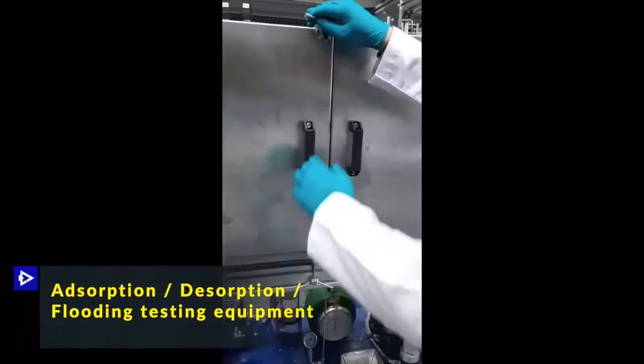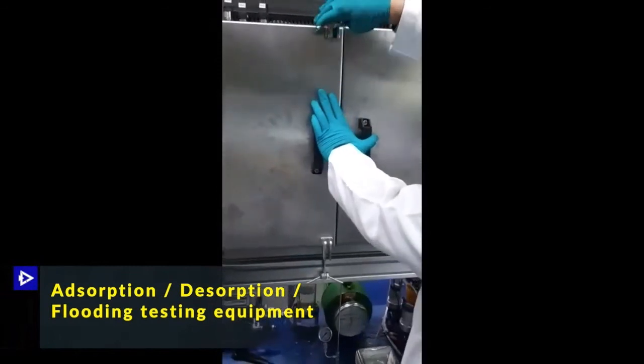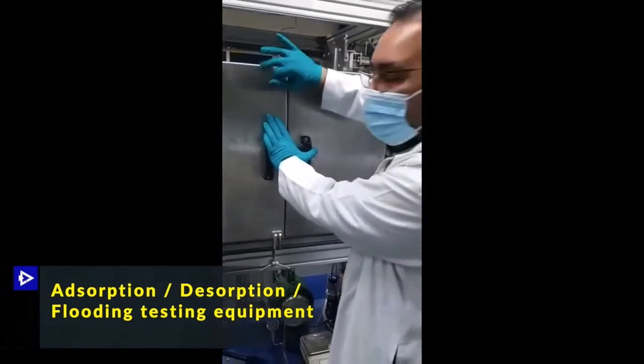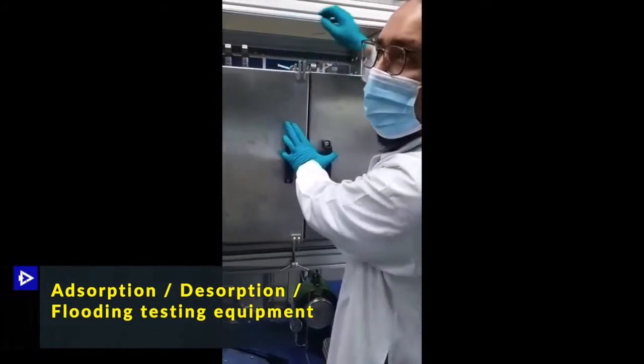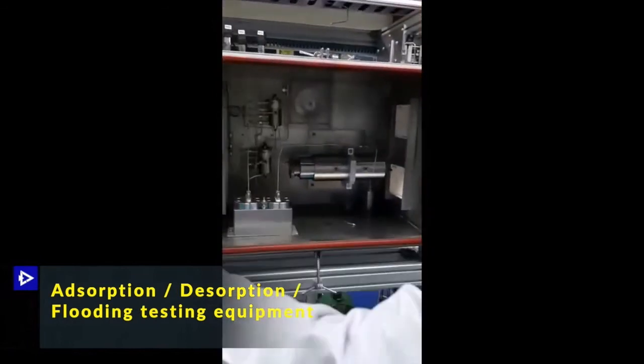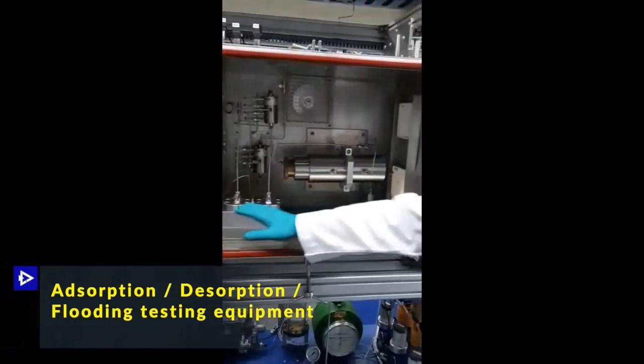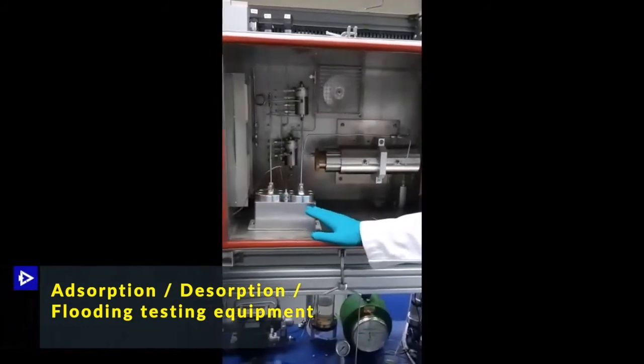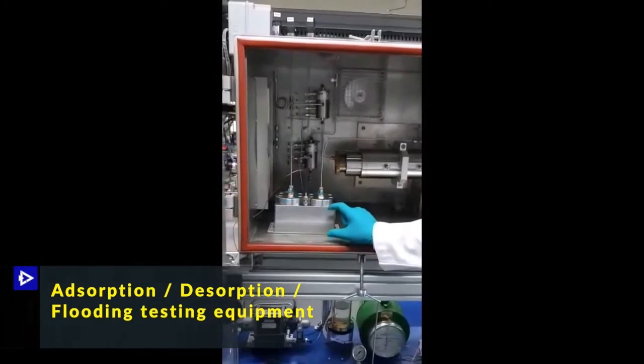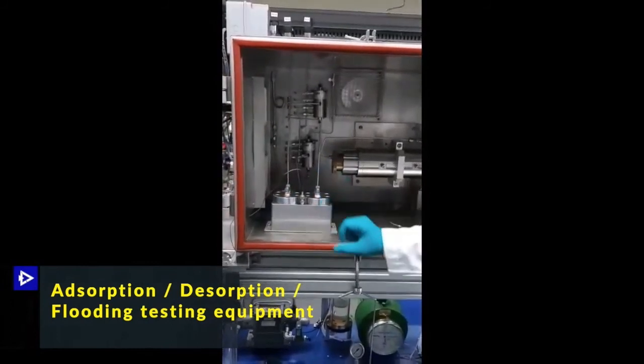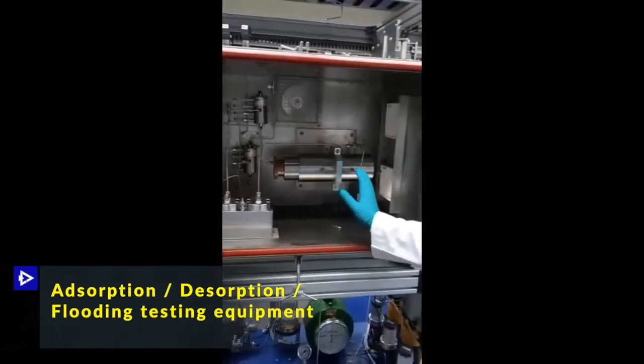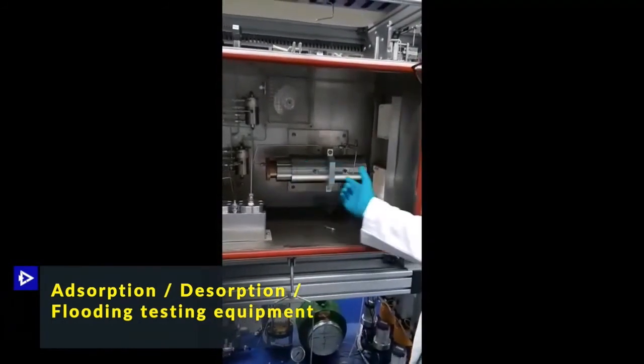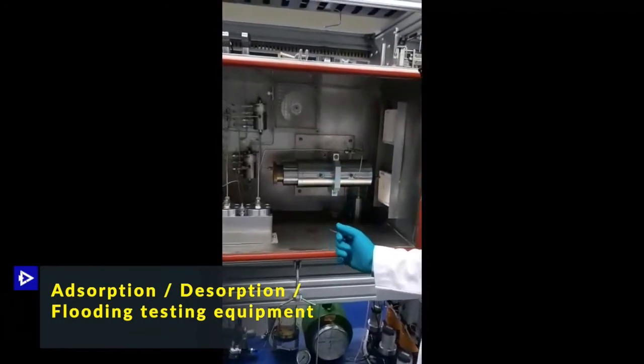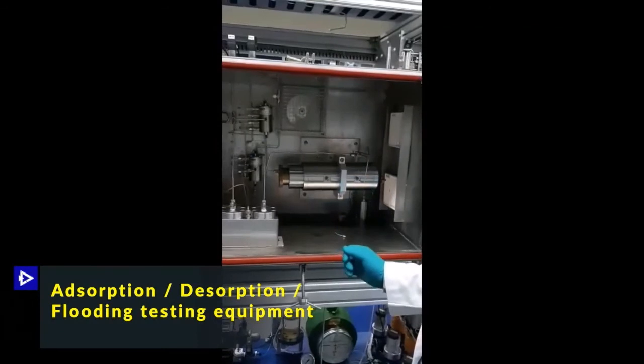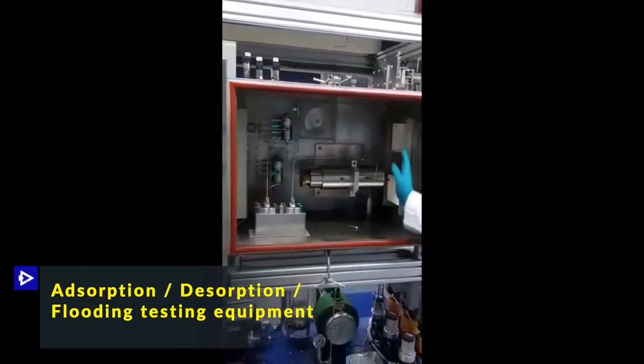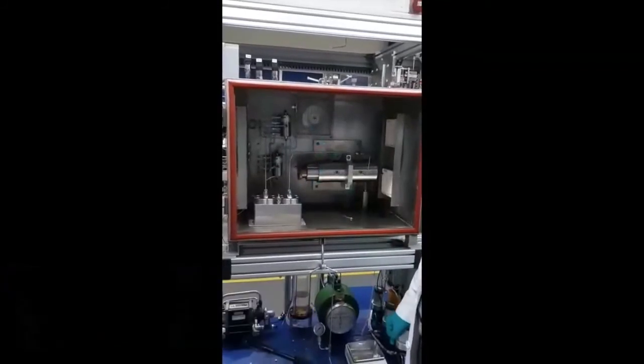This system can run up to 80 degrees centigrade and almost 150 bar, which is equivalent to 15 megapascal. These are the main parts we have in the system: our 2 canisters of adsorption system, where we can load 2 separate powder samples or even small core samples of shale. And here we have the flooding part, where we can load one almost 12-inch core of shale, almost 30 centimeters or slightly less. And here is the heating system, with a fan to distribute the heat at 80 degrees.